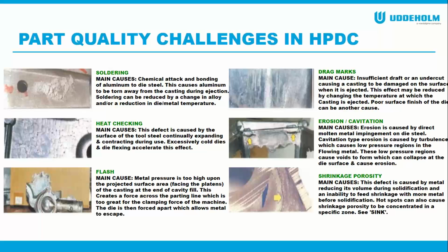Now we look at the first one, soldering, for example. For the most part, it is difficult to get away from. That's the chemical attack of the aluminum on the die steel, wanting to pull the iron out of the tool steel. So it's unavoidable for the most part. So when there is soldering, what typically happens in a die casting plant, for the die casting plants that still use die lube lubricant? You typically want to overspray the tool. So trying to resolve soldering, in turn, you're accelerating heat checking. So now you made an investment in a premium tool steel such as Dievar, and you're trying to resolve one issue, which is soldering, and in turn, you're deteriorating your investment and you're accelerating heat checking.